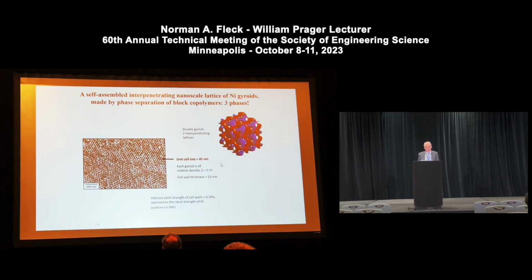And when you do that and perform an indentation test at this small length scale, you're limited in the type of test you can do. But if you perform an indentation test and deduce from that the cell wall strength of the nickel, you find that it has attained the ideal strength of the nickel. So this is an example where small scale gives you a much higher strength.